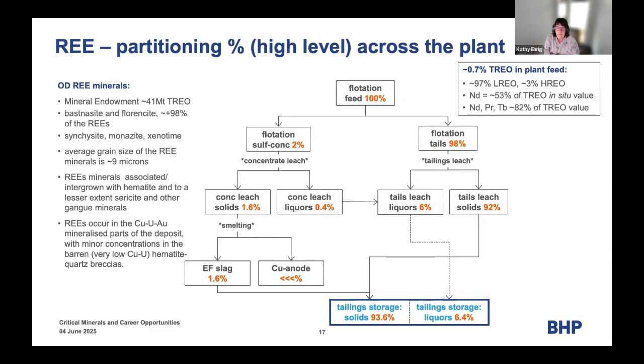But let's see what happens in the processing plant. We're just going to take that 0.7% and say that's 100% feed and do a very gross balance across here. These rare earths in a sulfide flotation circuit really don't recover to concentrate. It's the sulfide concentrate they're not exposed to. They go out to tailings. You can see that in the tailings leach residue after hydromet, 92% of the total rare earth oxides actually end up in our tailings solid. And there's 6% that's actually in the leach liquors.